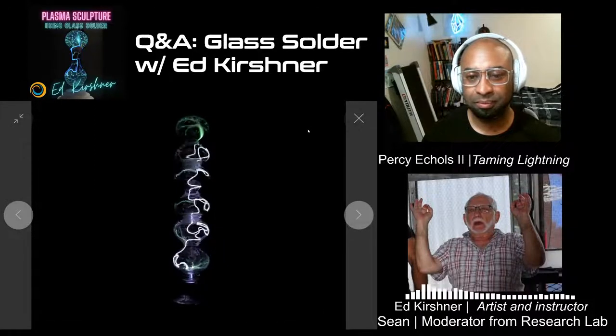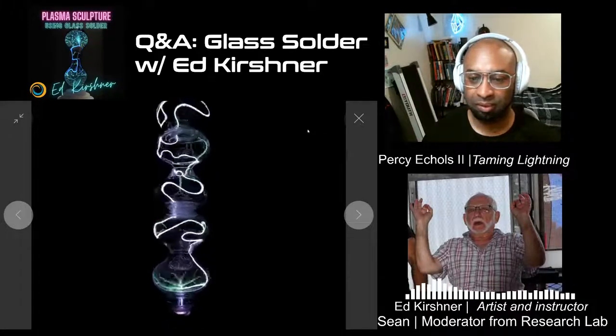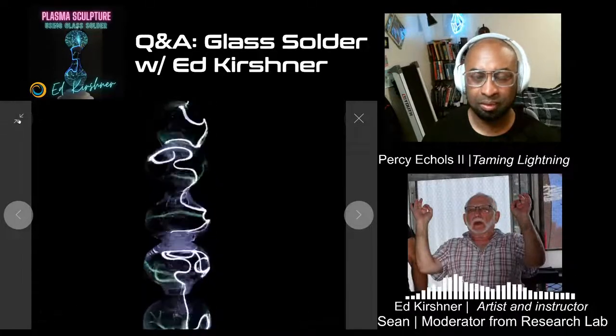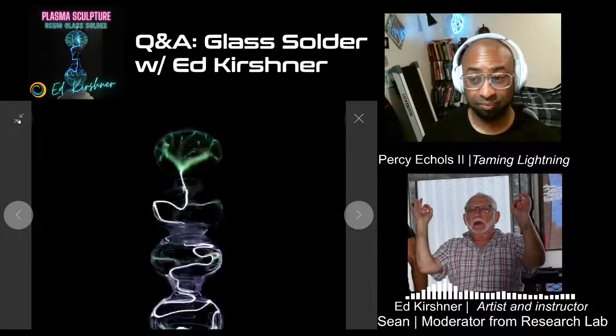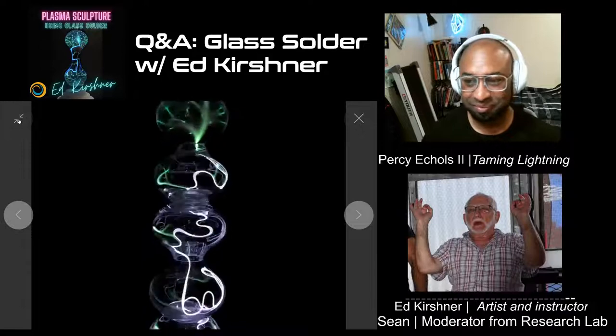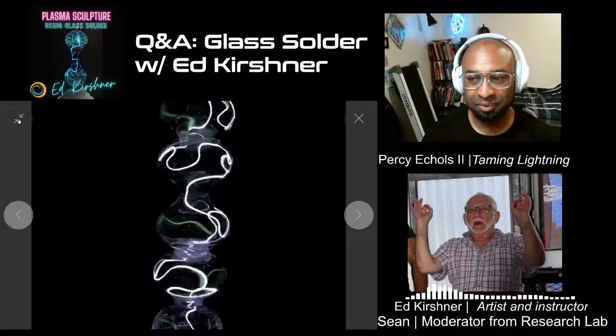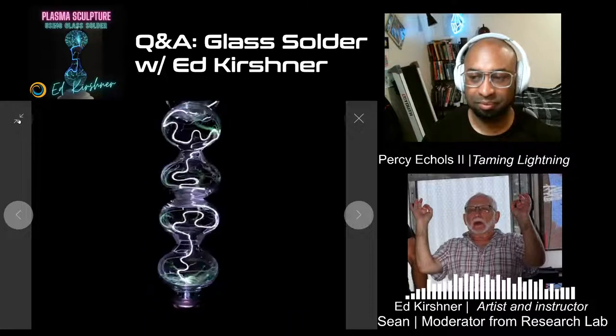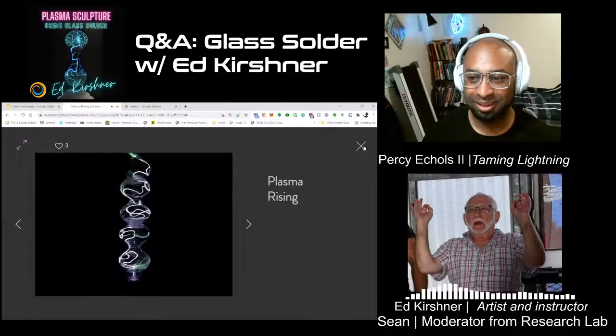And the solder itself will run whatever direction gravity is going. So even if you have it on an axis, it probably will just drip off. It will drip down, yes, but it's very viscous. So in some cases, I have actually put electrodes in perpendicular. And you can do that. It's another little gymnastics, but it does just what you said. And so you compensate, you put more solder paste on the top and let it flow down around the electrode. Yeah, I do not recommend doing it.